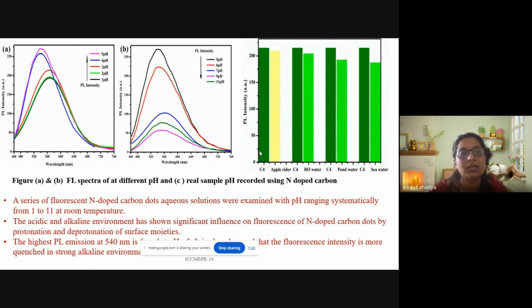There, different pH values were maintained by using NaOH or HNO3 solution, and the samples show good results. A series of the N-doped samples were examined, and their fluorescence intensity and shift can be observed from the figure with the changing pH value. The highly intense fluorescence is found at pH 5.